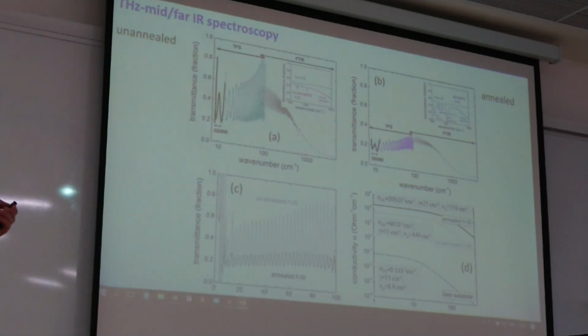And what is interesting, for annealed silicon we have stronger modulation of transmission, and for the unannealed one, because of stronger absorption of sulfur impurities, we have less transmission, much less. And this is illustrated here, for example, in the terahertz range. This is transmission of annealed silicon, and this is transmission of an unannealed one. And we can extract